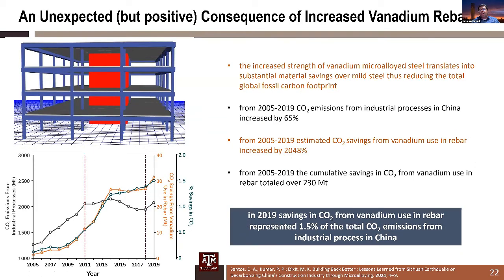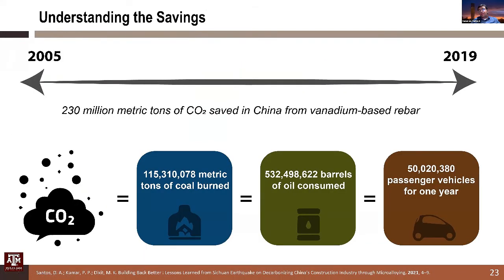And an unexpected but positive consequence of this is that by using higher quality rebar, we're seeing massive increases in the savings of carbon, because you're having to use much less steel, less concrete. Compared to a baseline situation where nothing had changed, there's almost a 2000% change in CO2 savings over time from 2005 to 2019. The 2019 savings in CO2 are about 1.5% of the total CO2 consumption. So 230 million metric tons of CO2 is a very large amount. And these are some ways to benchmark it: about 50 million passenger vehicles per year, if you think about the volume of the savings here.